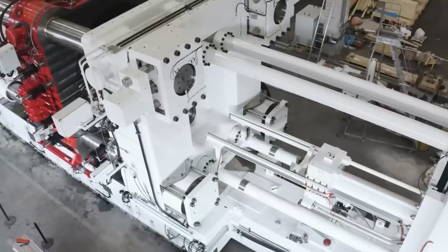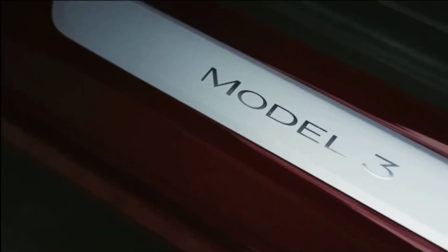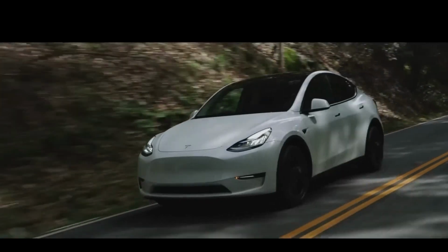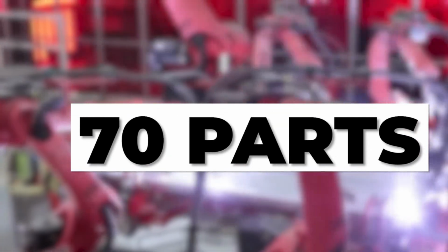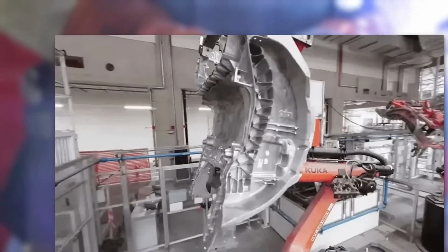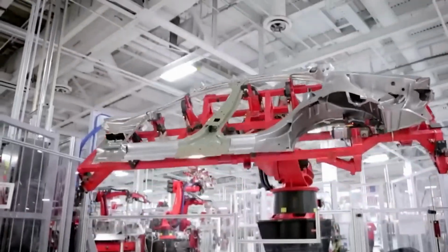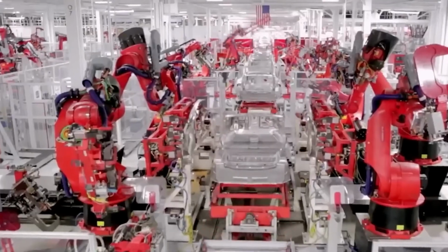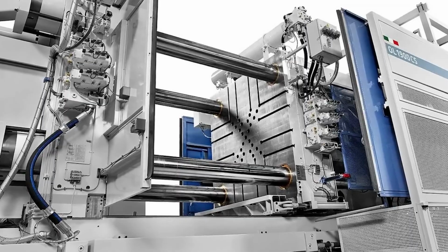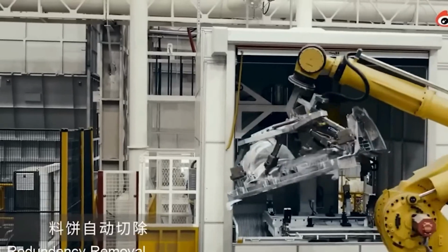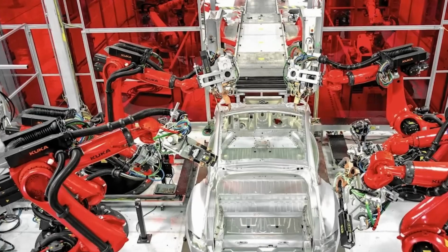Finally, the excess material is trimmed from the casting and is X-ray checked for quality. Then lastly, there is a final machining phase that adds the fine details like threading for fasteners. The speed of this operation is mind-boggling. At its peak run rate, the Giga Press can produce one casting every 45 seconds, with a maximum output of 1,000 castings per day. These Giga Press machines are now ubiquitous across Tesla Gigafactories and have changed the landscape of